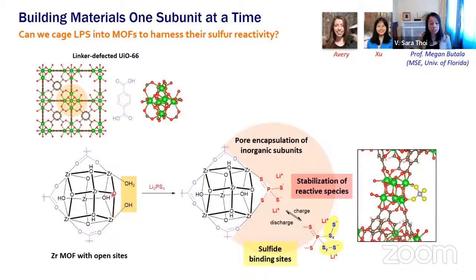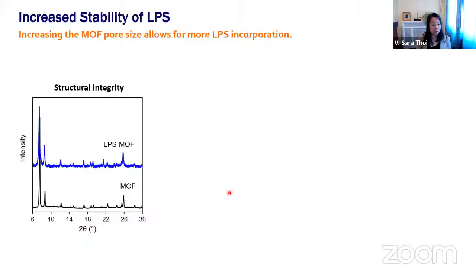We could then imagine that if we could replace that terminal linker with our thiophosphate, we now have a way to protect the thiophosphate inside this pore and then do our charging and discharging cycle within our metal organic framework. That was the hypothesis. We wanted to see if we could actually incorporate LPS into our materials without degrading it. And we indeed show by XRD, X-ray diffraction pattern, that the structural integrity of the metal organic framework is maintained largely after introducing LPS.